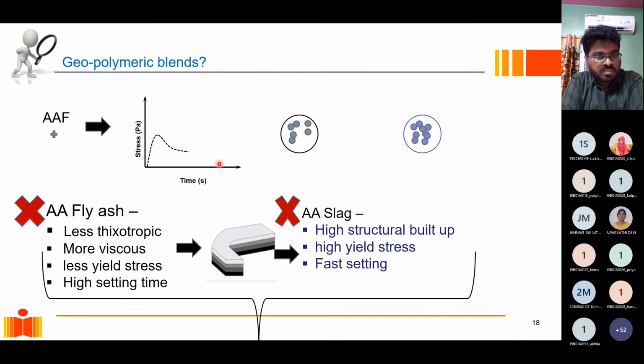So basically, when we're talking about these geopolymeric blends, when we mix fly ash and slag, we find that if I use only fly ash, it has very low thixotropy. That means it doesn't build up its structure after shearing. It is very viscous and it has a very low yield stress. That means the effort required to initiate flow is very small, which means if I place this material, it will slowly lose its shape, and that is not desirable.